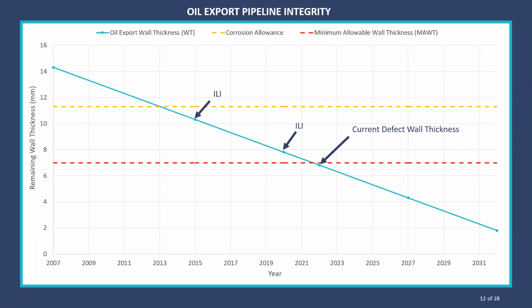As Rosie mentioned earlier, we've noted MIC and microbial activity upstream, so we suspect they're MIC, especially as we know corrosion inhibitor has been good in life for this pipeline. So the first thing we'd recommend is doing a more detailed defect assessment on these to tell you how far you can actually operate to with wall thickness.